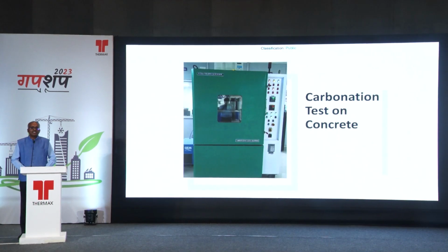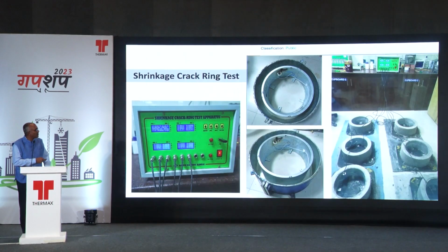Of course, the carbonation test is very rarely done, where carbon dioxide reacts with the free lime, calcium hydroxide, to form calcium carbonate. That per se may not be affecting the structure, but in the presence of moisture, when carbonic acid is there, you will find that the alkalinity of concrete is reduced. So the alkalinity of concrete has to be maintained. The pH value has to be roughly around 12 to 13, so that a passivity layer is formed around the reinforcement bars, so that it has a longer life.